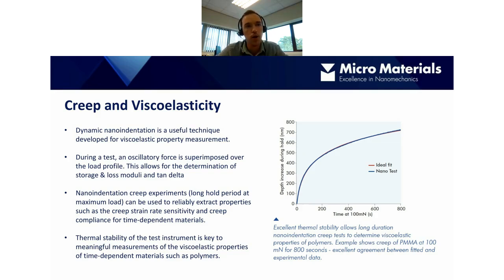So we can perform a nanoindentation with a long hold period, or what we sometimes call creep testing. This can be used to extract properties such as creep strain rate sensitivity and creep compliance for these time-dependent materials. So the thermal stability of the test instrument is important. I described earlier about thermal drift and how we minimize that. This is particularly important for these types of tests where the indenter is in contact with the sample for a long period of time. In the example here, this is a creep curve on a polymer material. This is 800 seconds, which is quite a long time, and we can perform creep tests that are even longer than that. So it's important, especially for these tests, that we have a system and an environment that is thermally stable.